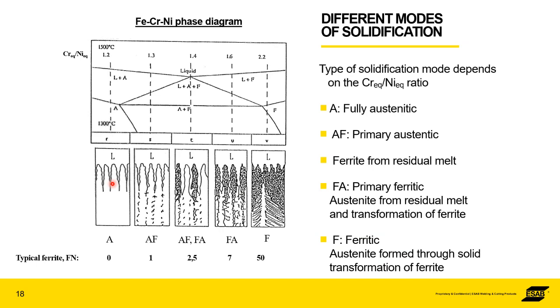With the fully super austenitics, the solidification mode is primarily austenitic. So there's no phase transformation in there. It's austenitic, and there's no room for ferrite. So there's no room for any impurities to be dispersed or to be compensated for. And this has to be taken into consideration. So this is the chemistry behind what's happening when you're welding.